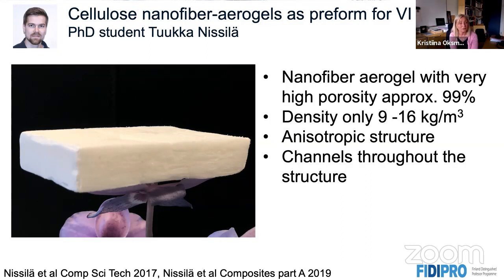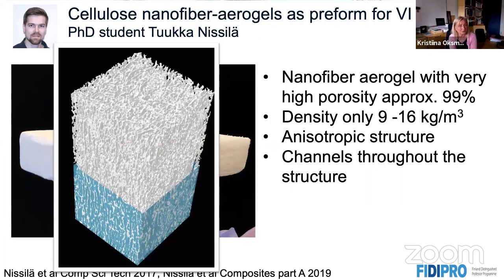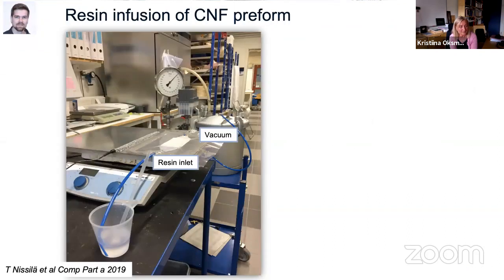And this is because ice crystals are growing through the suspension, and then this ice is sublimated, freeze-dried, and we have these channels through the structure, which are helping us to get the resin in. And here you can see a computed tomography image of this kind of material. And our resin infusion setup for this nanocellulose preform.